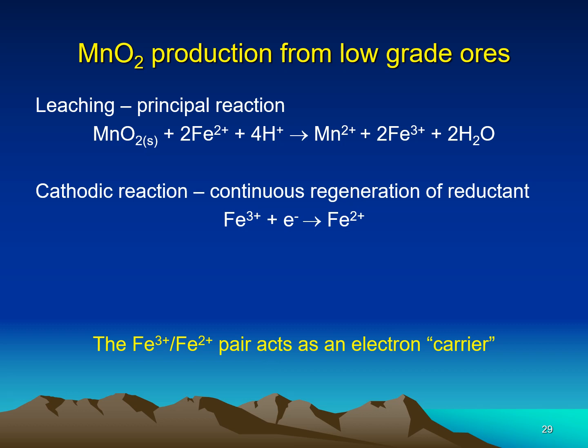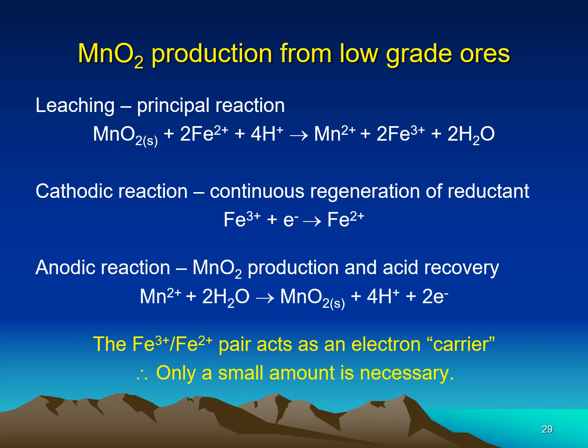And this ferric-ferrous pair acts as an electron carrier to and from the manganese particle. We can use only a small amount of ferric ion, ferrous ion, since this is going back and forth in the cathodic compartment of the reactor. And on the anodic side, the manganese is oxidized to manganese dioxide, and we recover the acid at the same time.